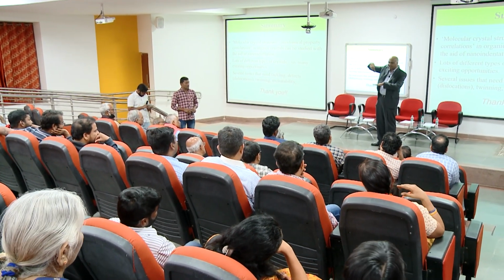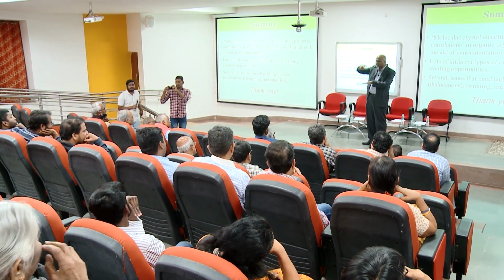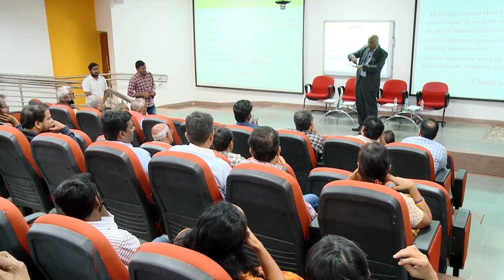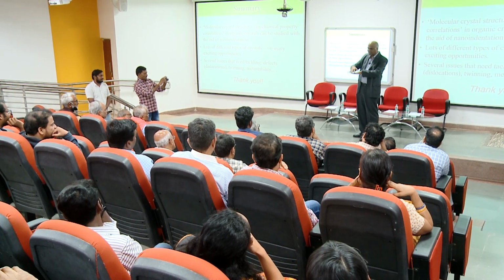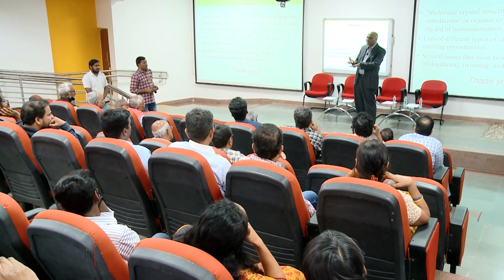What they do is take a flat surface and take something which is an indenter, whose tip is typically diamond or tungsten carbide, much harder, and you poke it. You apply 10 kilogram force, you poke it, remove it, and then you measure the imprint made. So the imprint divided by the force applied gives you the hardness.